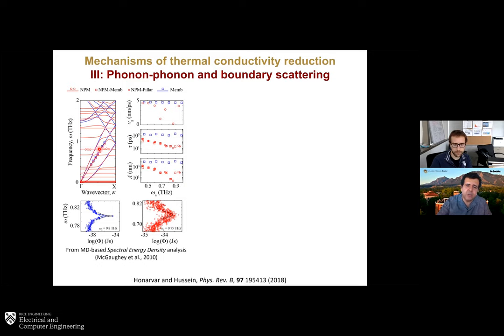So you can see here in this picture, we track that line of phonons. You see these are the group velocities. This is the lifetimes, and they drop a bit, as well as the mean free path. You can get the mean free path from the lifetimes using the group velocity. So they drop a bit, and that's shown there in the quality factor of the resonances associated with each of those phonons. However, as long as this is done in moderation, in principle it should be fine. It should not undermine the very wave effects that we are utilizing.